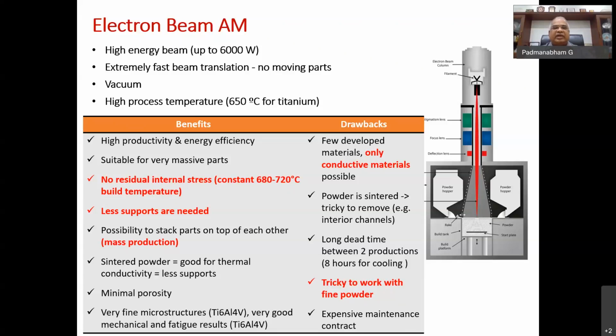So that's why I wrote here no residual internal stresses, because of the constant build temperature, irrespective of which layer you are building. And since there is already a cake formed in the bottom, you don't have to specifically create a support structure. When you have overhangs that you want to build, you have to build a support structure, and then on which you have to build a feature. But here you already have a cake which acts as a support structure, so you don't need to specifically build a support structure. And because of the speed, it can be used for mass production.